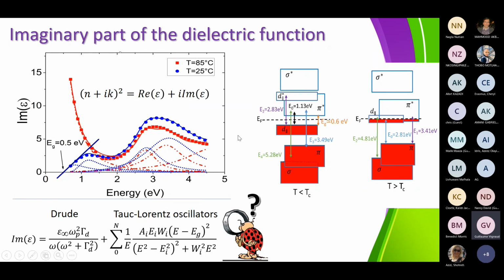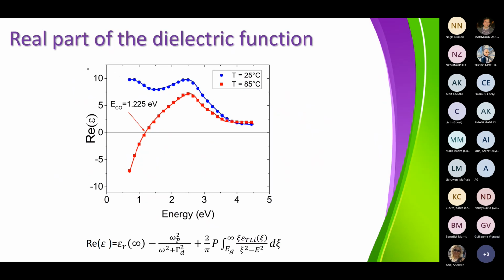And if you go now into the metallic structure, because you are in the metallic structure, it means that the Fermi level is located in the top part of the conducting band, and you don't have any more gap. So Eg is going to be 0. So you destroy the gap of the semiconductor, and you can calculate also the different transitions from the different levels inside the material. So this is why, once you have done the ellipsometric measurements, you can really get, first of all, the index of refraction, the refractive index of the material, but additionally, you can get the dielectric function of the material. And from the dielectric function, you can get very good information about where the energies are located in the material.